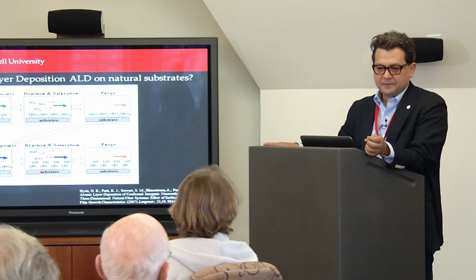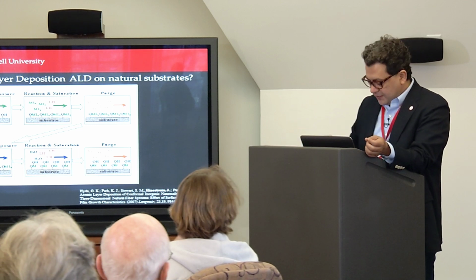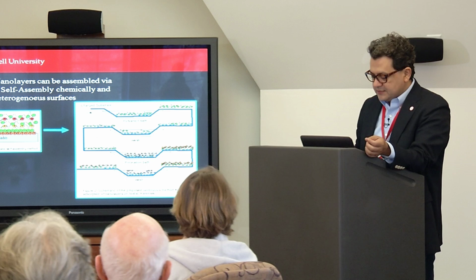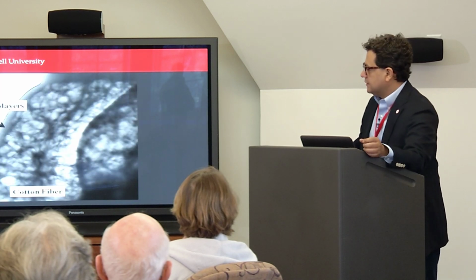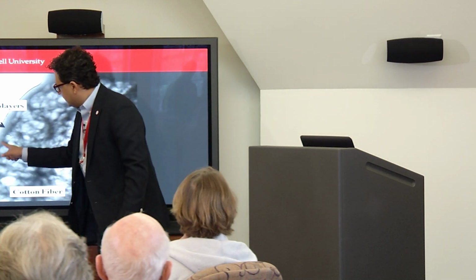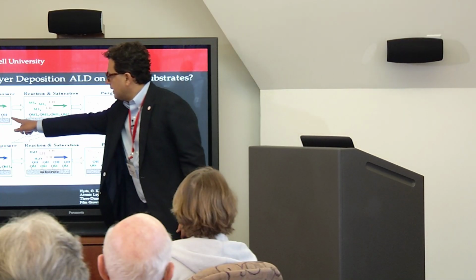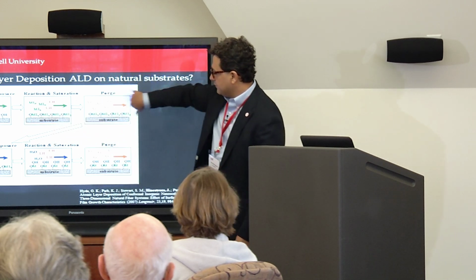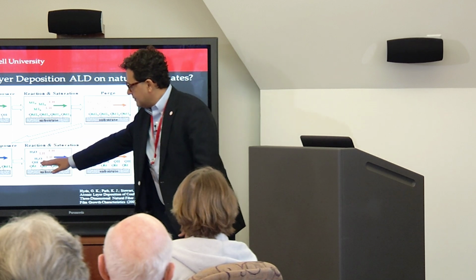So how do you solve the problem of cotton not being flat? Okay, so the way we did it is we actually created functional groups in the cotton. So we create functional groups here that will work as an anchor and will trap the polymer at all points. And we did the same for the atomic layer deposition. We functionalized the groups on the cotton, have the reaction with the metal, remove the excess, put water again. Again, we have OH, and then we can do it one by one. Except that this time, they are not 20 nanometers. They are not measured in nanometers. They are measured in angstroms. You guys remember how many angstroms in a nanometer?